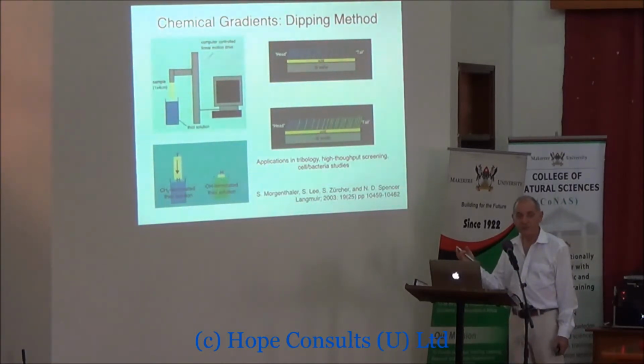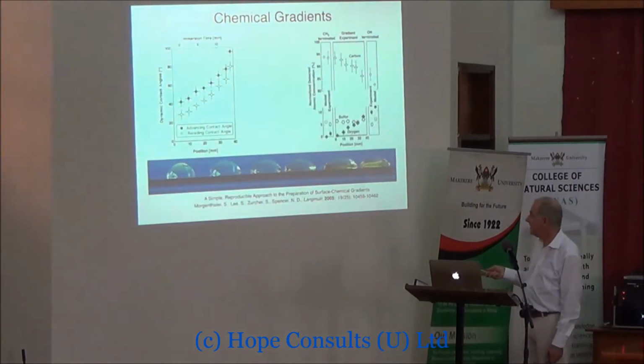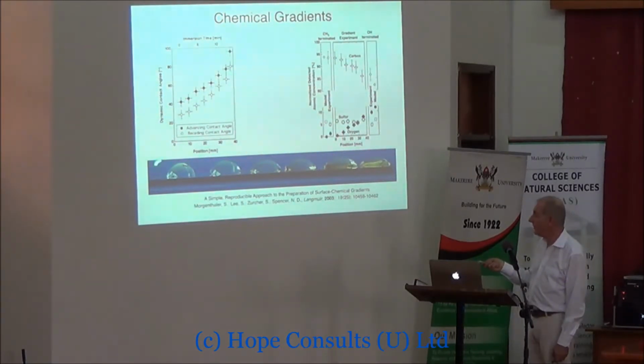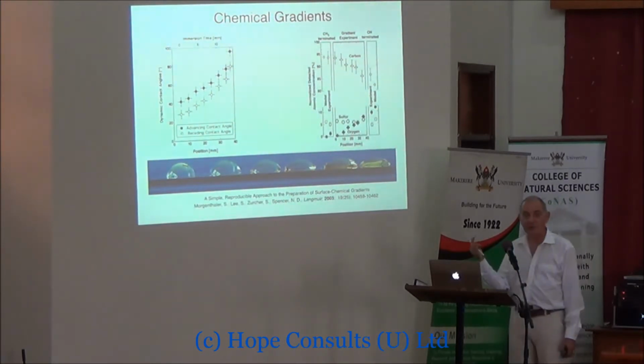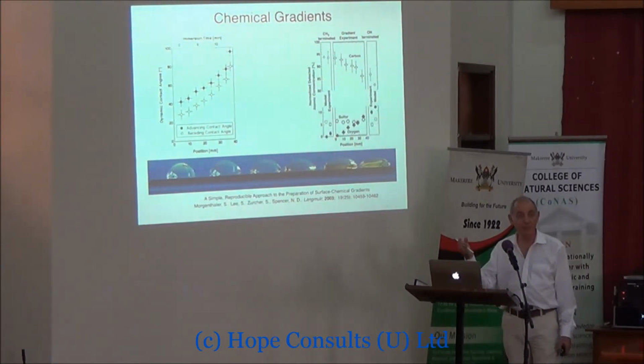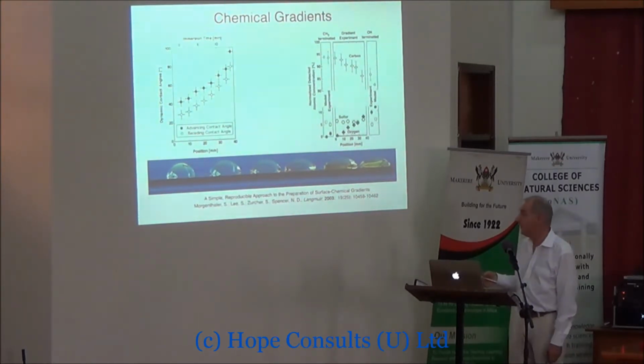Now, if you make that surface chemistry have different wettabilities, that means that you can have a hydrophobic behavior at this end and hydrophilic behavior at this end. So not wettable at this end and very wettable at this end. And you can use this for a number of different things. You can look at the effective wettability on some process, like the adhesion of bacteria to a surface, or the behavior of cells on a surface, or tribological behavior. But you've got all of these different surface chemistries there on a single sample, and that means that it's like doing a high throughput experiment to examine one of these gradients.